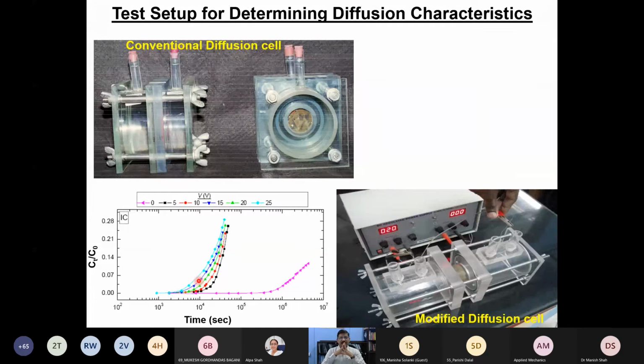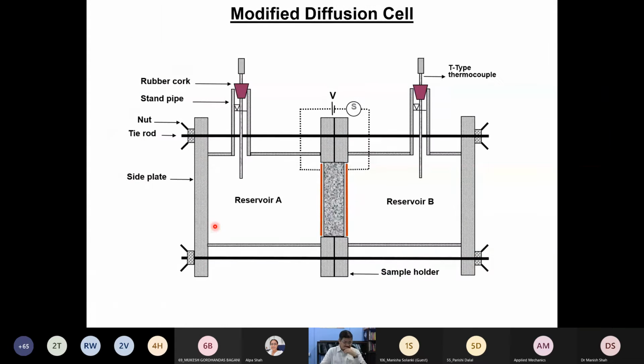Now you may ask a question: is this particular setup giving a diffusion coefficient? It's not going to be called a diffusion coefficient, it's basically a percolation coefficient. Once you have a percolation coefficient, we are able to back calculate the diffusion coefficient. So that means that by applying the voltage, the same phenomenon, I can really finish it in a short period of time. So by using this particular modified cell, where a chemical gradient is imposed, in addition to that, there is an electrical flux also being imposed against this one.